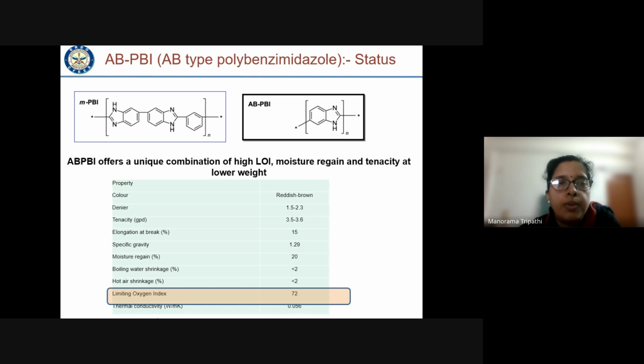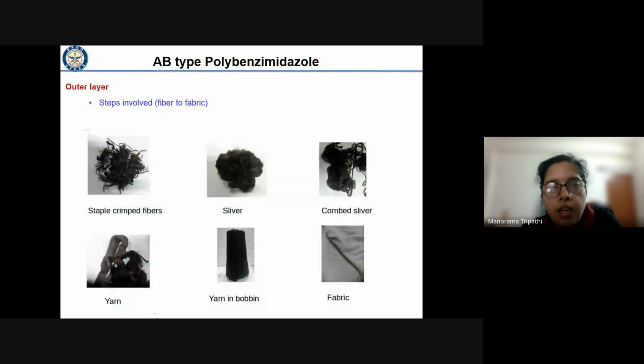Now I will discuss some results which we have got with AB type polybenzimidazole. It has a unique combination of high LOI, moisture regain, and tenacity at lower weight. LOI is of the order of 72. This is the outer layer. These are the steps involved from fiber to fabric conversion. This is the staple crimped fiber, then sliver. All of you must be knowing this.